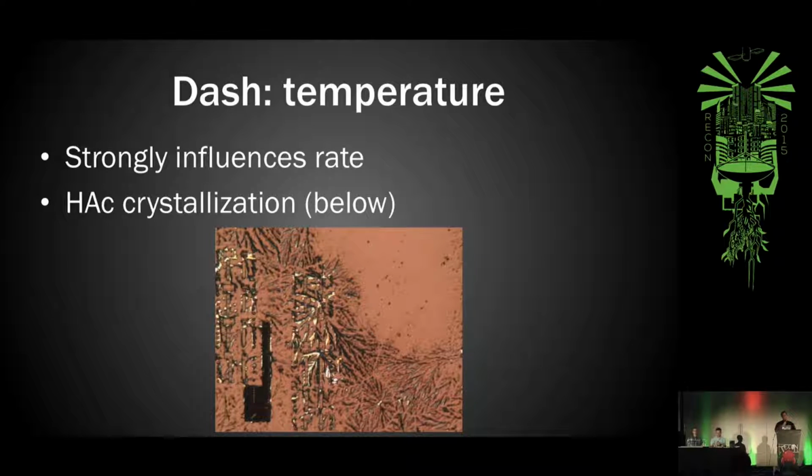And one of the very interesting properties about this liquid, or solid rather, is that it melts at room temperature. So depending on how you look at it, it's either a solid or a liquid. And this becomes a real problem because if it's not a hot day, this will actually precipitate, cover your die, and actually interfere with the reaction.